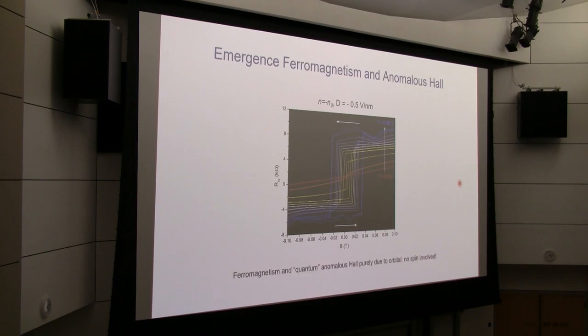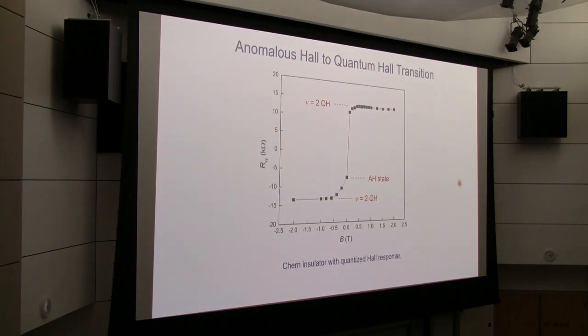So that means, indeed, it breaks time reversal symmetry, and all the holes actually prefer to go to one valley. So this type of magnetism is fairly different from the conventional magnetic material we usually see, which is dominated by spin. In this case, spin plays very little role. It's dominated by the orbital motion of the electron in the system. And if you look at the quantum Hall signal, you find that it is quantized quite well at nu equal to 2 state. So that tells us it is actually a Chern insulator with a Chern number equal to 2.